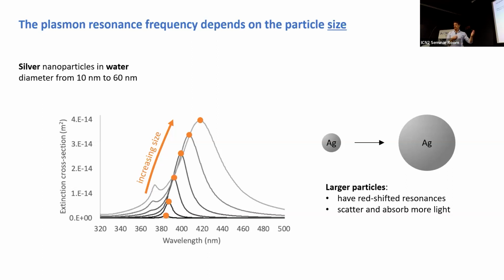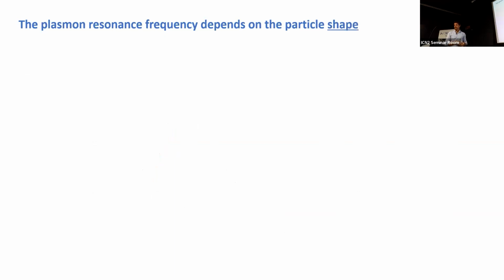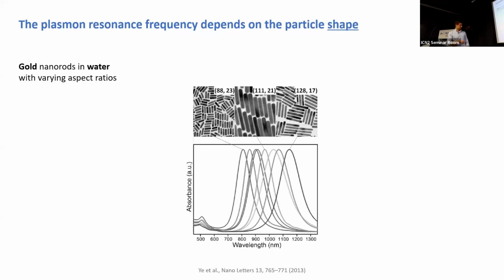Now we can also tune these resonances by playing with the shape. So colloidal chemists, they have an infinite range of nanoparticles they can make. And so, for example, we can make gold nanorods in water with different aspect ratios. This is 88 by 23, 111 by 21, 128 by 17. So they're getting kind of skinnier and longer, and the aspect ratio is increasing. And so you see that the plasmon resonance shifts, let's say, from the red part of the spectrum or near infrared to the infrared part of the spectrum. We can play with that.